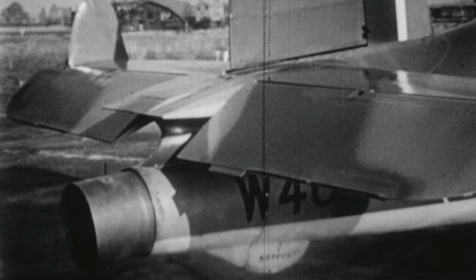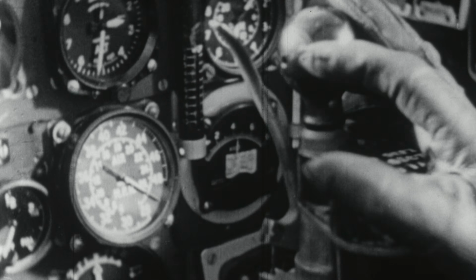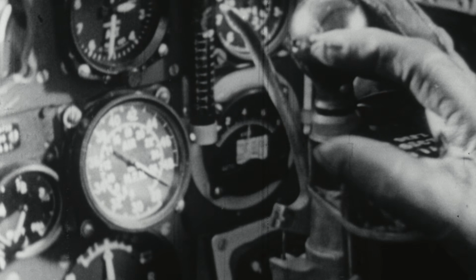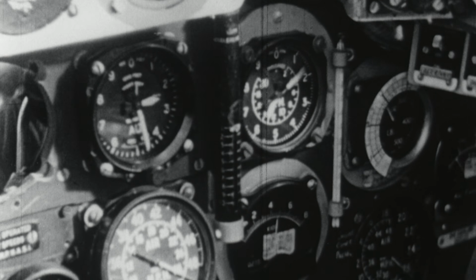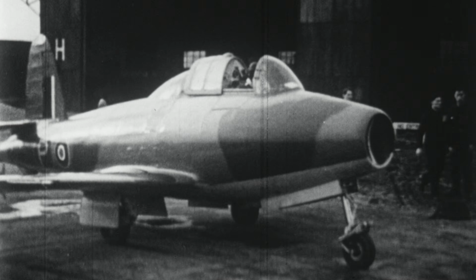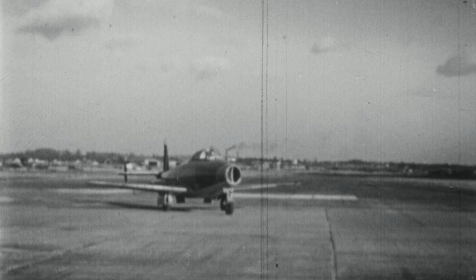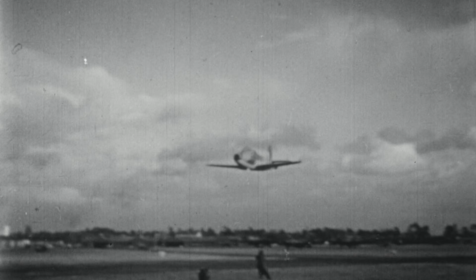The first was that the gas inside the engine only reached temperatures of around 780 degrees Celsius, which was one of the reasons it was inefficient. And the second was that it was only allowed to fly for up to 10 hours. Any longer, and it was too likely parts inside the engine would fail. And both of these drawbacks were largely due to the steel turbine blades.